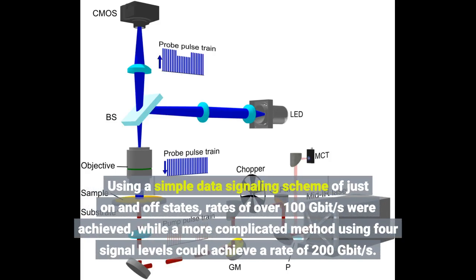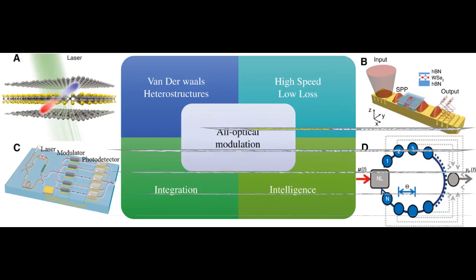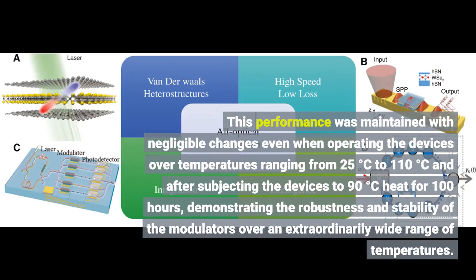Using a simple data signaling scheme of just on and off states, rates of over 100 gigabits per second were achieved, while a more complicated method using 4 signal levels could achieve a rate of 200 gigabits per second. This performance was maintained with negligible changes even when operating the devices over temperatures ranging from 25 degrees Celsius to 110 degrees Celsius and after subjecting the devices to 90 degrees Celsius heat for 100 hours, demonstrating the robustness and stability of the modulators over an extraordinarily wide range of temperatures.